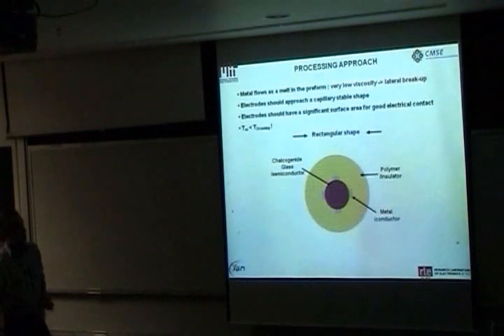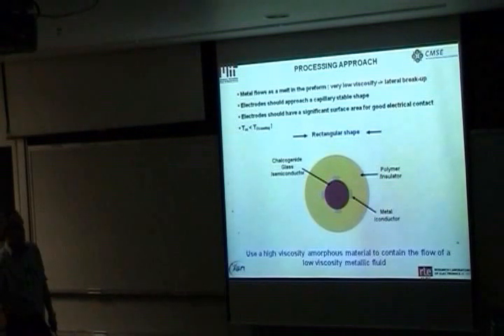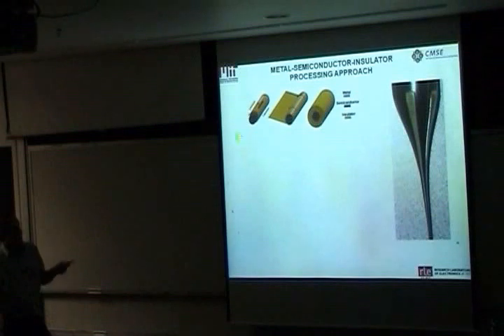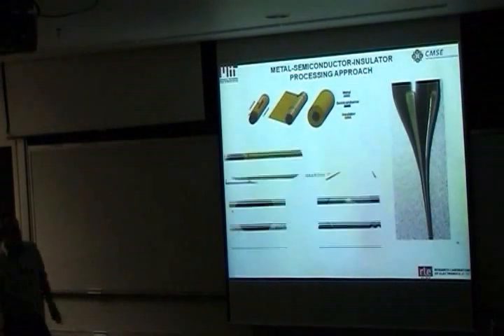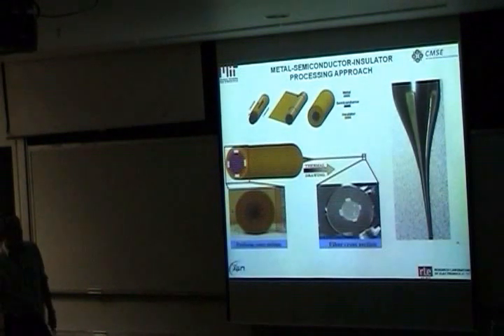These were not very ordered, but you could get very ordered structures as well. And then realizing that it really is capillary breakup that is driving it. And so initially we designed electrodes that are much closer to their cylindrical equilibrium structure. And so this is how we make them. We actually start off with a semiconductor core. We put a polymer shell on it, insert the electrodes, consolidate it, and then get this drawn into a fiber.